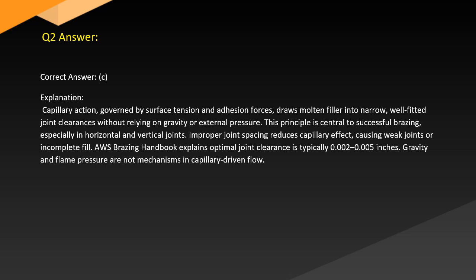Improper joint spacing reduces capillary effect, causing weak joints or incomplete fill. AWS Brazing Handbook explains optimal joint clearance is typically 0.002 to 0.005 inches. Gravity and flame pressure are not mechanisms in capillary-driven flow.